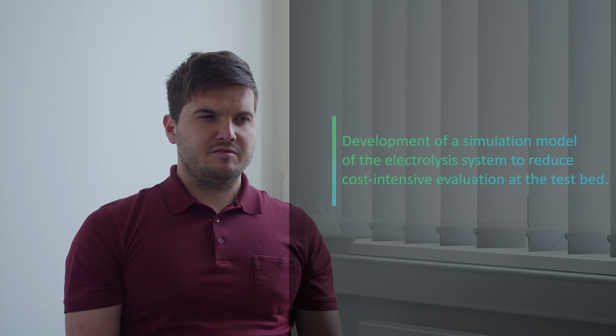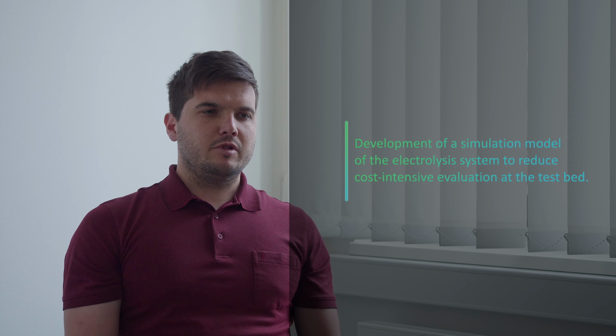With this setup, harmful as well as insufficient operation states were identified, and together with all results gathered, the operation strategy was optimized. The optimization of the operation strategies was carried out by Prüfrex with a simulation-based approach, which included the development of a simulation model of the electrolysis system to reduce cost-intensive evaluation at the testbed. The model was subsequently used for optimizations of the layout, the control strategies for longer lifetime of the stack, and a sensor virtualization approach for lower system costs. During the project, two stack generations were developed and tested at our testbed at HiCenter. While the first generation stack showed challenges that needed to be addressed, the second generation stack performed well with low catalyst loading.